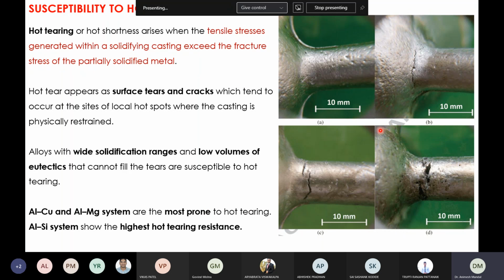If it is a very fine crack, you can use certain NDT techniques. Otherwise, if it is a very macroscopic crack, you should be able to see it with your naked eyes itself. These hot tears are very common in the 2 series and 5 series, that means aluminum copper alloys and aluminum magnesium alloys. You hardly see this in aluminum silicon alloys.